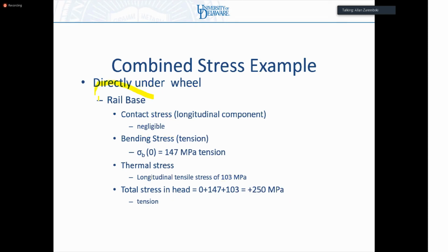If I'm under the wheel, I'm looking at the rail base. My contact stress is negligible. I'm neglecting the stresses due to the sleeper, which are small, spread over a much larger area. The bending stress is now 147 megapascals tension, because it's in tension under the rail, and the longitudinal stress is still 103 megapascals tension. So it's 0 for my contact stress, plus 147 megapascals for my tensile bending stress, plus 103 megapascals for a total of 250 megapascals in tension on the base of the rail.